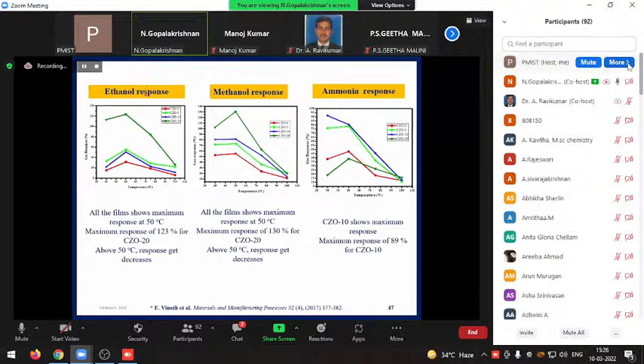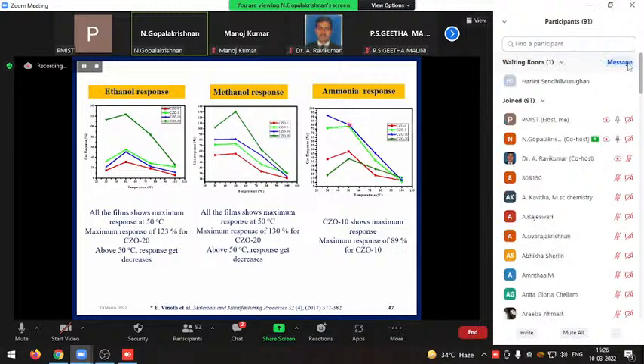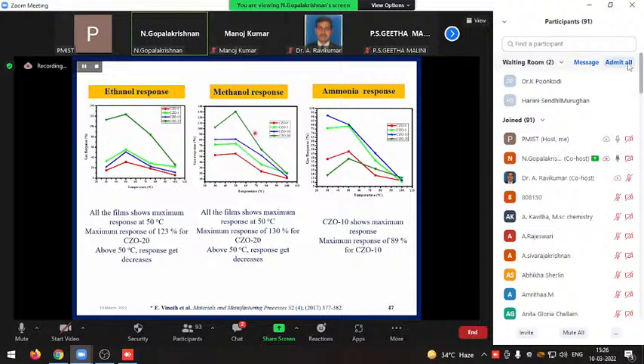So for ethanol gas here, and for methanol, we saw the response. The ammonia gas also we saw here. The maximum response we got is 89% for ammonia here, and here almost 130% for the methanol. For the 20% dopant, the green one, again we got 123% for this 20% doped cadmium zinc oxide thin film.